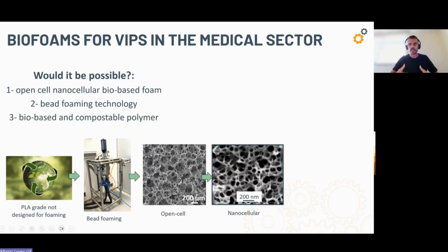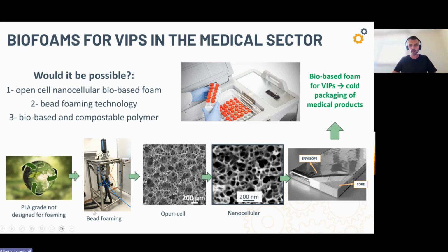The thing is, okay, we know now that we can reduce the time and we can reduce the pressure to produce a foam using very tiny micropellets. But is it possible to produce a foam with an open cellular structure and a nanocellular structure needed in an efficient vacuum insulation panel using the bead foaming technology and using a biopolymer, in this case a PLA grade not designed for foaming? If we are able to fulfill all these requirements, we would have a very promising material for the core of a vacuum insulation panel, and then a very promising material for the refrigerated transport of vaccines, for instance.